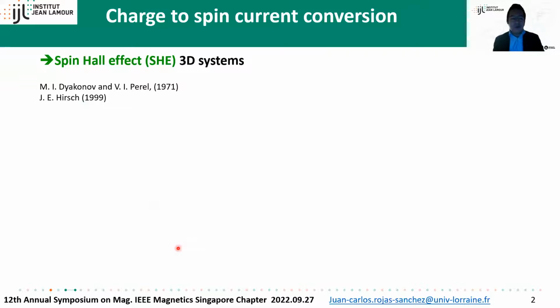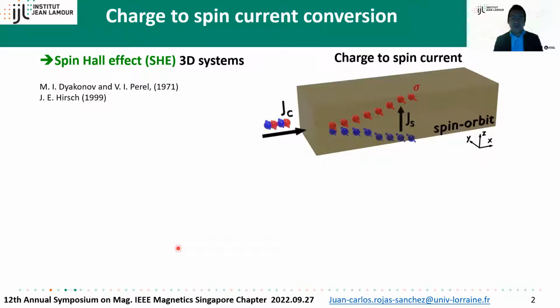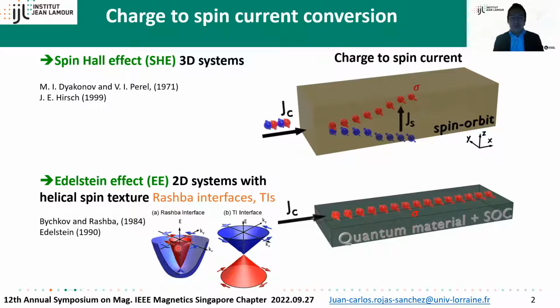So let's quickly recall, because I saw many talks also on spin current conversion, spin Hall effect, and Rashba-Edelstein effect. We can have this spin current conversion in materials with a strong spin orbit coupling. Then we have the spin Hall effect and its reciprocal, but also in some materials with spin texture, like Rashba interfaces or momentum locking in topological insulators, we have the Edelstein effect and the reciprocal effect that also exists.